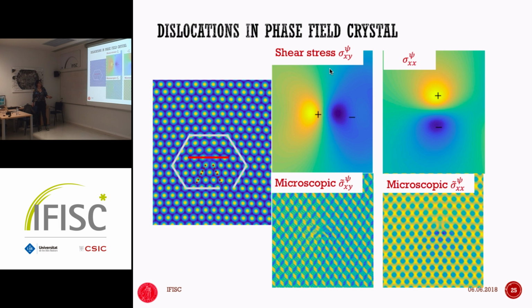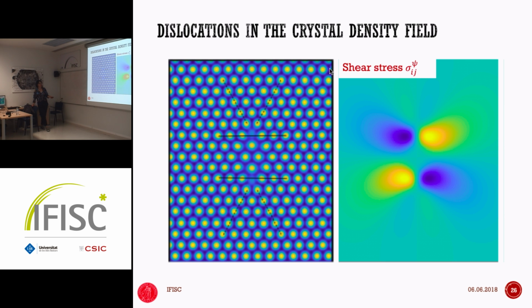It's not a true singularity, as we will see, because this order parameter is smoothed. We are at a scale where we cannot really have a singularity. But if you coarse-grain all the way into the continuum, they will appear as singularities. At this mesoscale, there is no singularity, which is to say that the dislocations have a finite core. If you shrink the core to 0, then it becomes a true singularity.